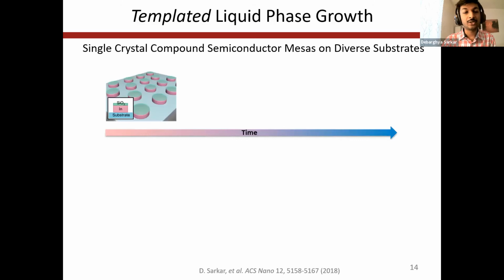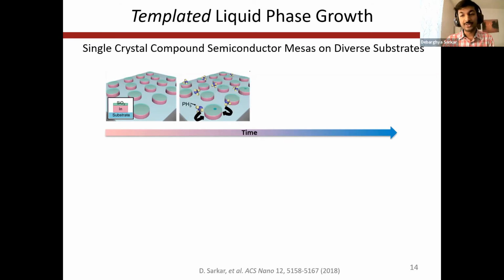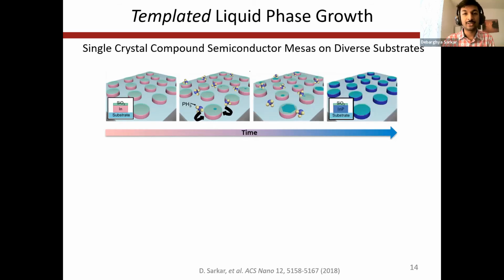So we start with indium mesas on a substrate capped with silicon oxide. And this entire structure is taken to a growth chamber where it's heated at a temperature above the melting point of indium, and phosphorus is introduced in the form of phosphine. Now, critically, this phosphine flux is controlled to ensure single nucleation in each template, so that with time, each nucleus grows as a single crystal until it consumes all of the indium and transforms it to single crystalline indium phosphide, so that the final structure is single crystalline indium phosphide mesa growing directly on an amorphous substrate.